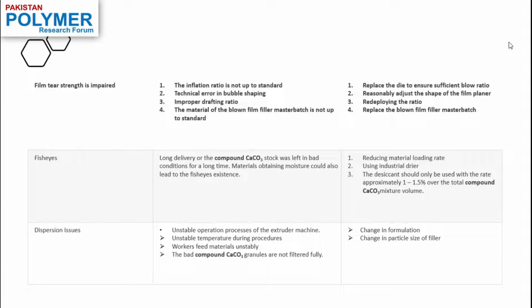Another problem that is very common and that is related to your raw material and can be highly dependent on your calcium carbonate is the fish eyes that occur in your blown film. The fish eyes occur because you might be using calcium carbonate that has been left in a bad condition for a long time, and the material has got moisture in it, and this leads to the existence of the fish eyes. So it's really important in these conditions to check if your material is moist or not. In case it has got some moisture, you should be reducing the loading of your material, because the lower the loading rate of your material, the more time it will get dried inside the extrusion process.